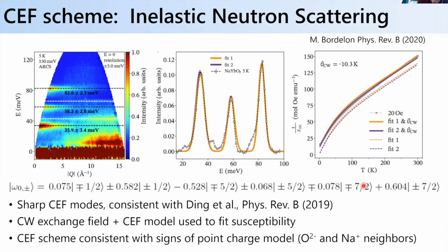Okay, so the next thing we can do is look at the single ion properties of the system, and we should try and prove that indeed we have a well-separated ground state doublet relative to the temperatures that we're working with. And so we can do inelastic neutron scattering measurements, and this is just a color map showing the energy transfer to the system as the neutron scatters as a function of the momentum transfer. But we're talking about single ion physics, so you don't worry about the momentum transfer so much. Instead, you can just look at the energy levels. And what we see are 3 excitations, which if we do a one-dimensional cut, we can see these 3 modes. And these 3 modes are the excitations from the ground state doublet into the 3 excited state doublets, okay?